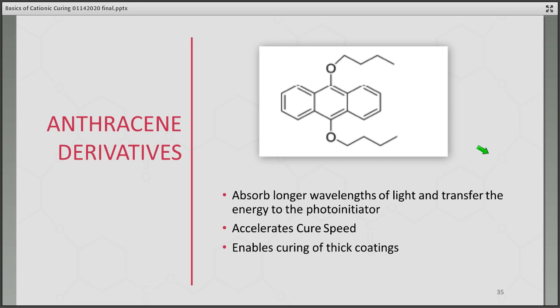I mentioned with the iodonium that you can use them with thioxanthones or other types of sensitizers. One that's probably most commonly used is the anthracene derivatives, and I have the structure listed here. These absorb longer wavelengths of light and then transfer that energy to the photoinitiator. So a small amount of these materials, the anthracene derivatives in your system, will accelerate your cure speed, and it also enables curing of thick coatings.